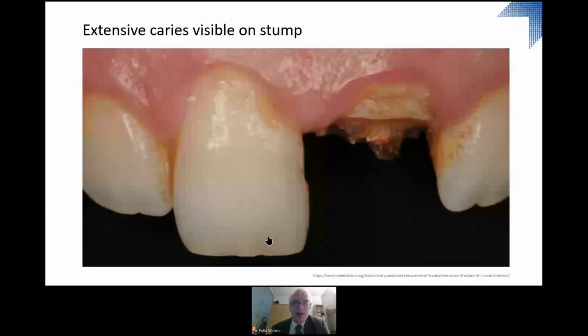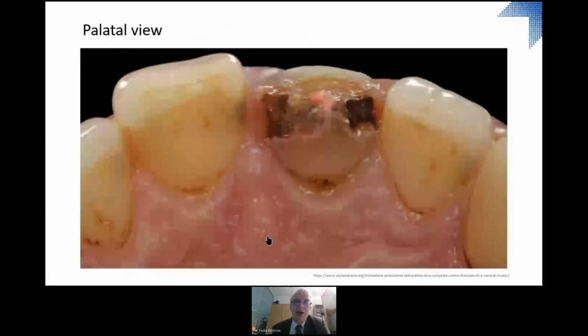And sometimes that's a little bit more difficult than other things. The good thing was he had still the other part of the broken off restoration. But the bad thing is, you can see there's a lot of caries here. This is why it finally broke. Obviously and likely the bonding system failed, and then you got secondary caries, and the whole restoration failed.